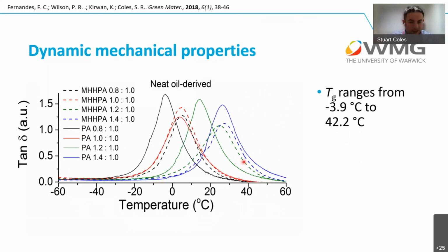We then calculated the Tg, and this is often one of the big ones that people look towards when they look at epoxies and structural materials. They look at the glass transition temperature: how stiff is it, what sort of operational range can we work in. And we found that the Tgs for this system were pretty low. We were going from somewhere around -4 degrees C up to 42 degrees C. Commercial epoxies are probably going to sit around 100, 80, 100, 110 is not unheard of. Certainly much higher than 42 degrees C.